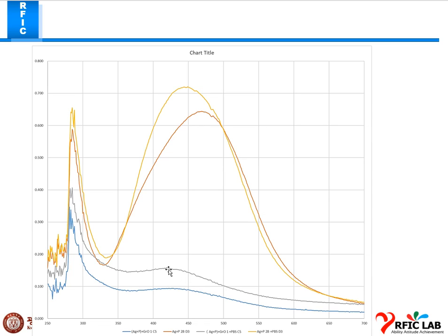So this result is not showing a good one. Simultaneously, I also checked the LSPR of only the Ag protein complex that is already defined, but we have to double check. Then we found that this red one is the LSPR measurement we got. The Ag protein complex measurement is quite good, better than the complex of Ag protein and the graphene oxide.